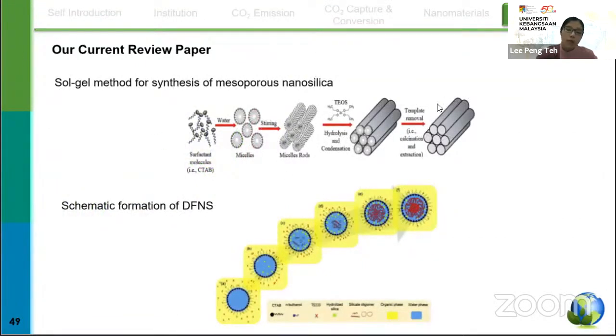In this slide, I would like to give you some ideas on how the sol-gel methods synthesize the mesoporous nanosilica and also the dendritic fibrous nanosilica. Here, the dendritic fibrous nanosilica is synthesized by using the microemulsion technique. So we have CTAB as a template, right? Then at the end, we will remove the template. TEOS is basically the silica precursor to produce the nanosilica.